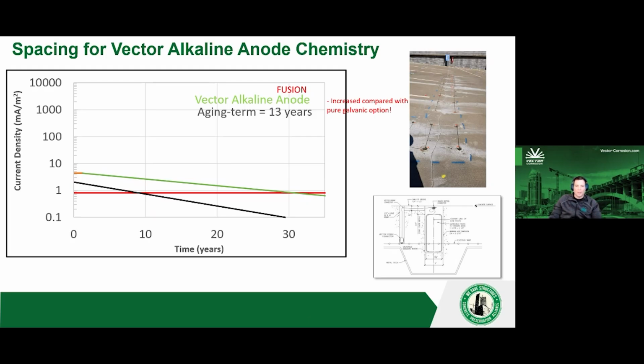One other cool thing about this structure and the way they did this repair is they were able to use somewhat limited dollars to the best of their ability. So VCS durability was brought out to help with the actual layout of the anodes. They did a more in-depth half cell survey and found the most corrosive areas and really hatched out and put little dots where they needed the protection. And I believe the installer here was Vector Construction, as well as Pullman was on site there as well.